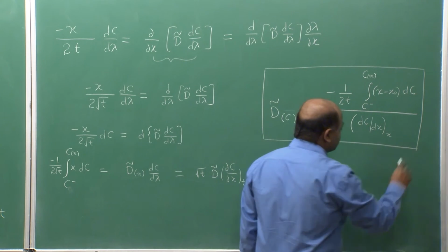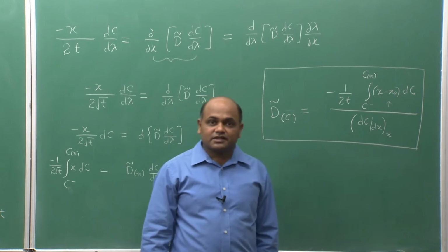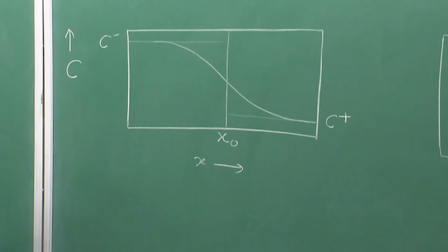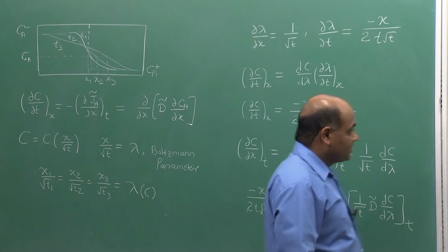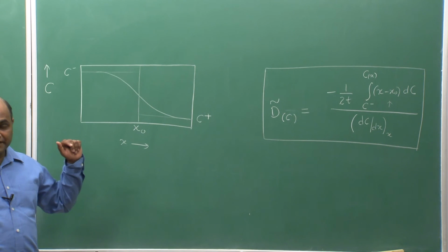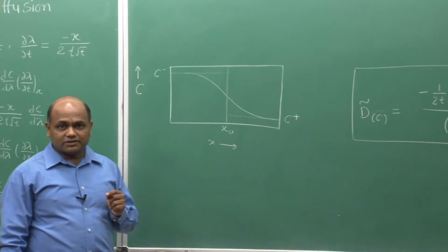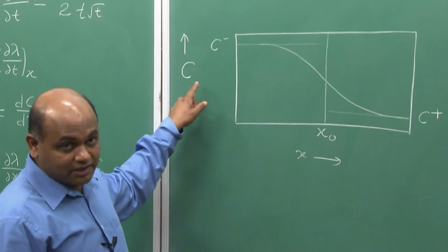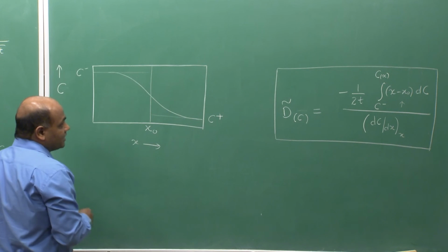and this gives the equation for binary interdiffusion coefficient. Now, what is this integral again? It is nothing but the area under the curve. So, if we consider this concentration profile again, remember we were talking about the concentration of A, and then we dropped the suffix because we are considering the binary system here, and for binary system to define any composition we just need one concentration variable. So, C implicitly we are assuming here it is Ca. So, this integral is nothing but the area under the curve.